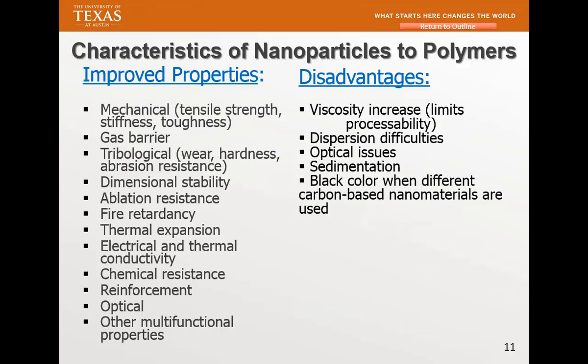The other one I want to caution you about is that some of these nanoparticles, especially ceramic, are very high in density. So when you stir it, it's really good. But when you stop, I'm just giving an example as thermoset, you don't cross-link it, well, all these particles are going to sink to the bottom. That's what I call sedimentation. So those are the things you need to watch out for when you disperse your nanoparticle into your polymer, and a lot of times with thermoset, you would like to disperse the best you can and immediately cross-link it. Then you will lock up all these nanomaterials in the resin, and you'll get some good product.